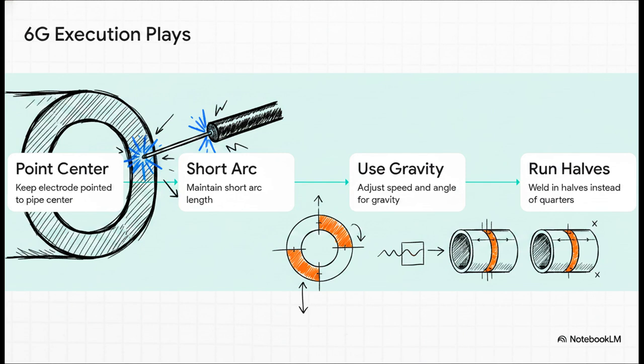Step 3 is crucial. You must account for gravity. On the bottom of the pipe, gravity is pulling your puddle away. On the top, it's actually helping you fill. So you have to dynamically adjust your travel speed and angle as you revolve around the pipe. Do not just weld square to the joint. And step 4, weld the pipe in halves rather than quarters. This significantly reduces the number of starts and stops you have to make, which, as we know, are prime real estate for defects.